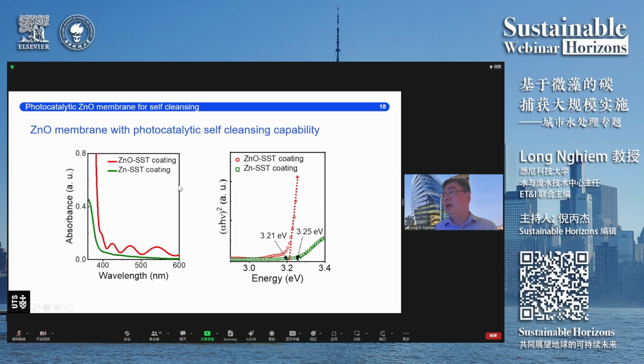When we check the transparency of the zinc oxide film, basically what we have done is we put a glass layer into the coating chamber. So the zinc oxide also coats the glass layer, and then we remove that coating layer so that we can check the optical property of the coating layer. And you can see that the coating layer is very much absorbing in the UV range with a very sharp absorption edge at around 380 nanometer. This shows very good photocatalytic property. And the Tauc plot also shows that our coating layer has a band gap of about 3.2 eV, which is really good for photocatalytic property.